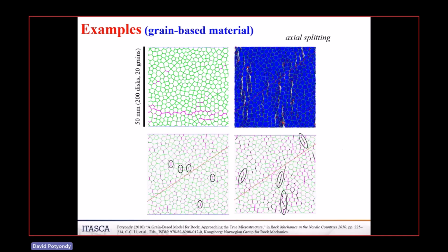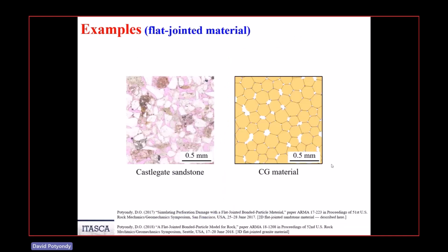This grain-based model was set up to have infinite strength inside the grains. So even without grain breakage, we're getting a very good calibrated response similar to something like a granite or a diorite. Okay. Now let's look at the flat jointed material for that same sort of thing.